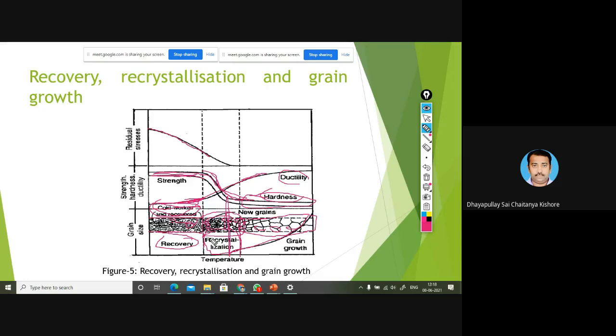Why are they strain-free? Because before recrystallization, cold working occurred. In cold working, the grains get compressed, and these grains have strain within the adjacent grains. Due to that, by increasing the temperature, new grains are formed, and the grains are strain free. So it forms new, strain-free grains by replacing the older grains, and that particular temperature we call the recrystallization temperature.